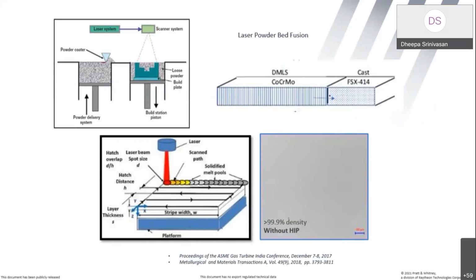So what we did is, as I told you, the base alloy was an investment cast FSX 414, that is a cobalt tungsten alloy, onto which we said, let us cut off the damaged part near the trailing edge and deposit laser powder bed fusion cobalt chrome moly, as you can see in the schematic out here. Then after this geometry is joined, let us weld these two together, the cast FSX 414 and the powder bed fusion cobalt chrome moly. Let us manually weld it, and then let us implement the part back into service after post weld heat treatment.